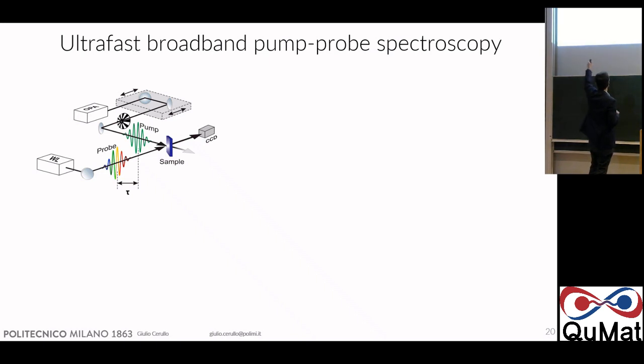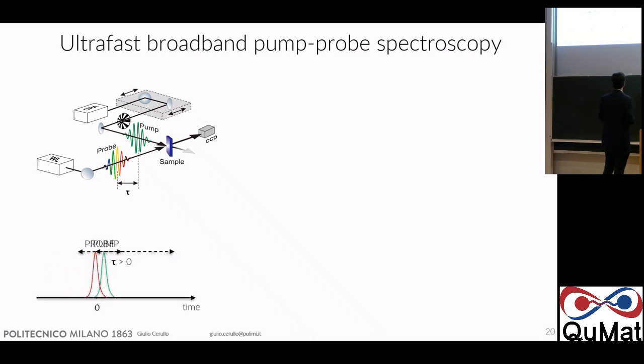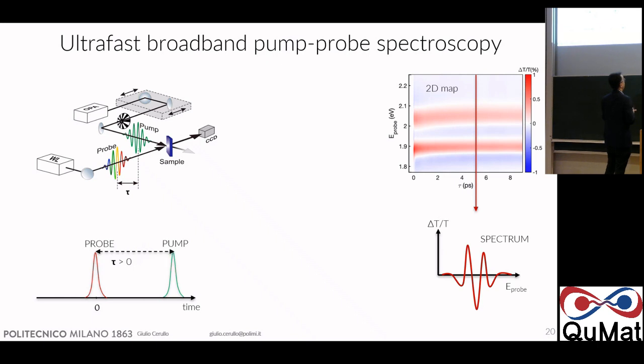Essentially, you have these two sources, these two pulses, which can be pretty short, and actually it's our specialty to make really short pulses, on the order of 10 femtoseconds or even shorter. And we change the delay between pump and probe from positive to negative. And what we measure is what you see here, a map of the differential transmission of the probe. Here you are measuring a spectrum, because typically we resolve the probe colors on a spectrometer. And here you see in time the delay.